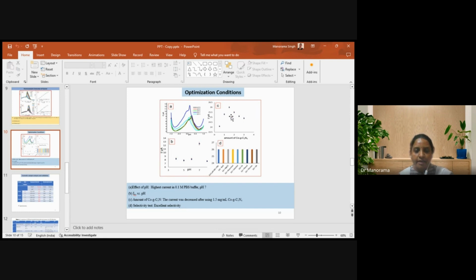And further, we have also studied the amount of cobalt doped graphitic carbon nitride, how much we have to utilize. So we have utilized different amounts of the cobalt doped graphitic carbon nitride, and in this condition we found that when we take 1.5 milligram per ml cobalt graphitic carbon nitride, when we mix, then the maximum current we obtained. But when we increase the concentration, the current decreases. It may be due to the formation of a thick film, or you can say the higher concentration of the graphitic carbon nitride. As we know, the graphitic carbon nitride is a little bit semiconductor. It behaves like a semiconductor, so current decreases. That's why we have taken the 1.5 milligram per ml. This we have optimized. Then we have checked the different